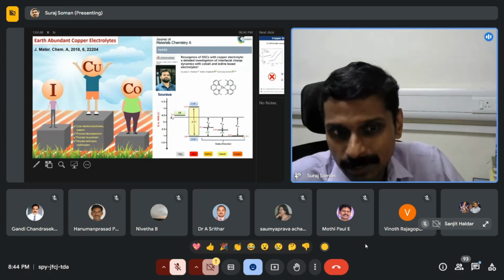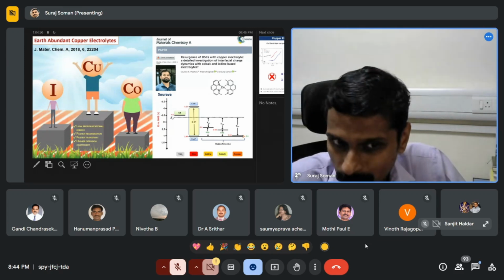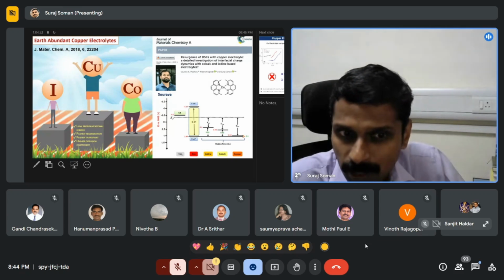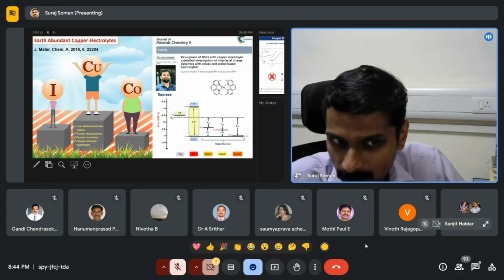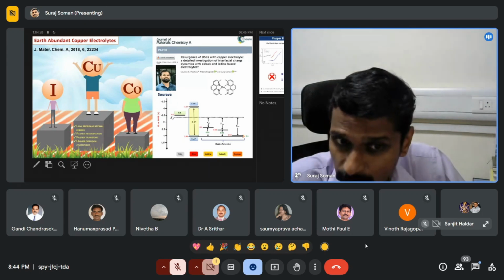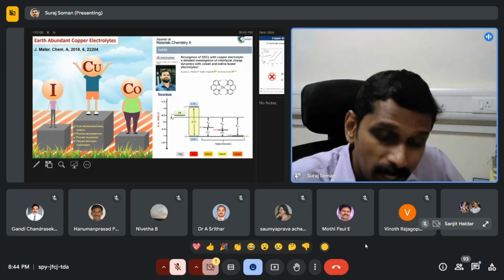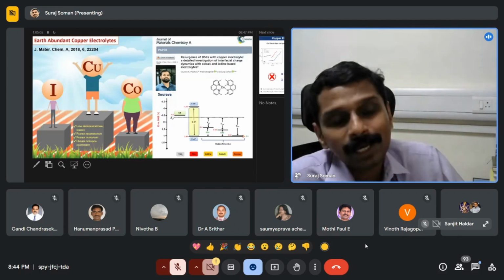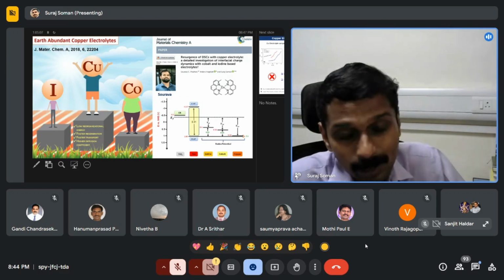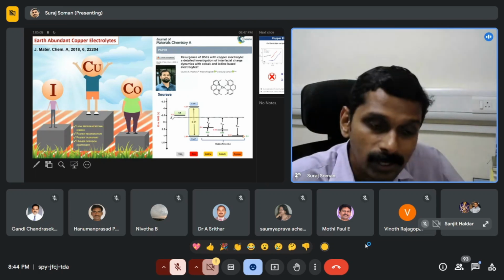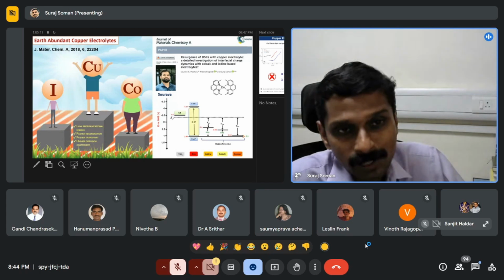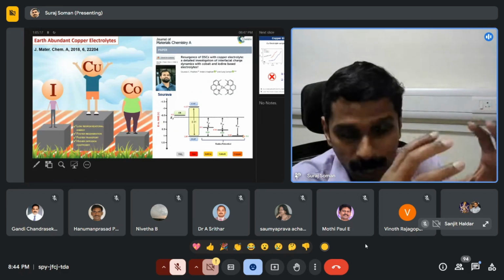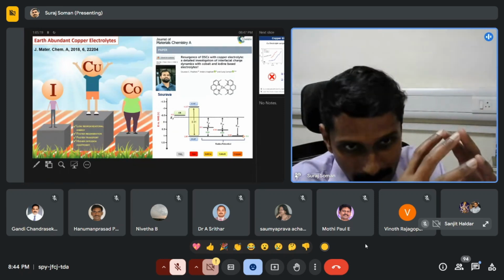But the problem here is that the moment you reach copper, you can see that this is having very close proximity with the ground state of your dye. So the driving force for regeneration is very low. But even with that minimal driving force, due to certain very critical things with the structural properties of these copper metal complexes, it is having a very fast interfacial charge transfer. The thing is that the copper is a tetrahedral system. You have 2 polypyridyl ligands attached to the copper metal center.